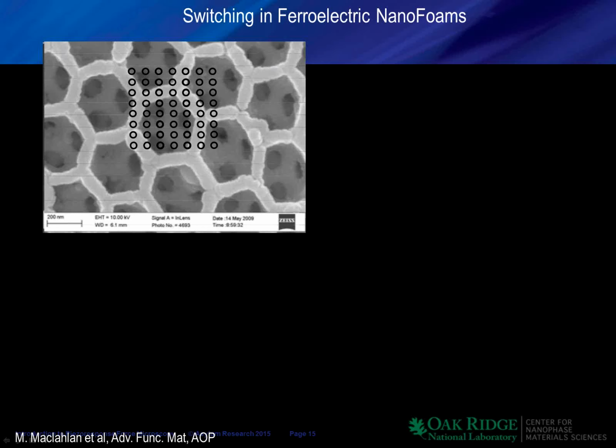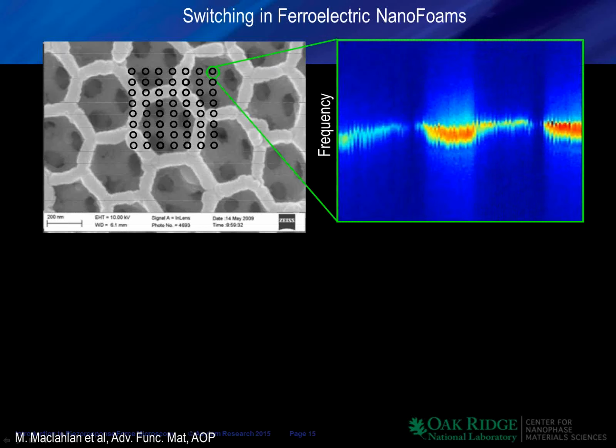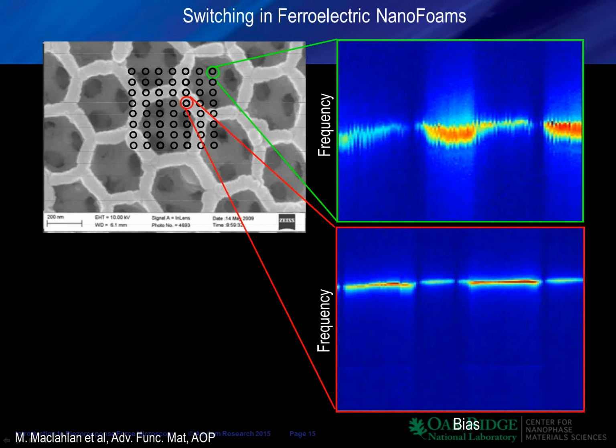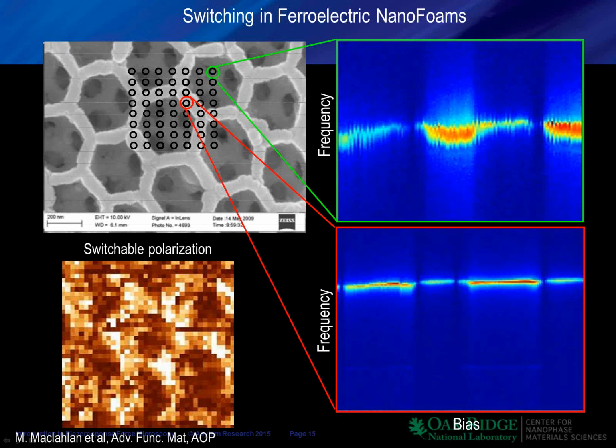So we create our lattice of points. We do measurements at a point which is nominally in the empty space, so practically the tip will touch by its side the edges of this nanowire. And we can measure a hysteresis loop here, but you can see that there is a tremendous variation of the resonant frequency and very strong noise. If we do the measurements over the solid wire, in this case the response is very well behaved, and we see clear polarization switching, almost constant resonant frequency, so the response is normal.